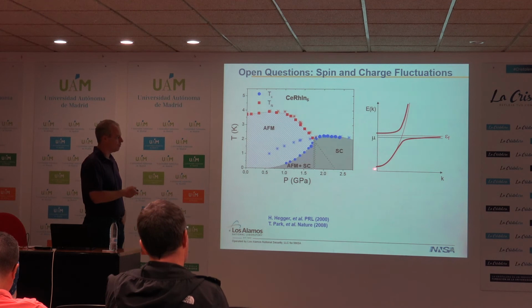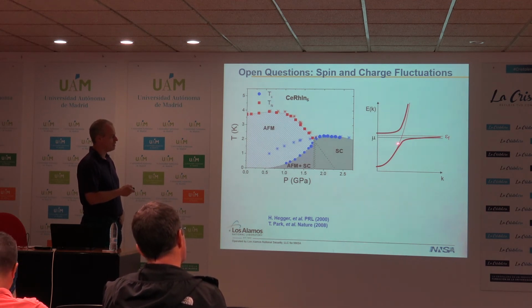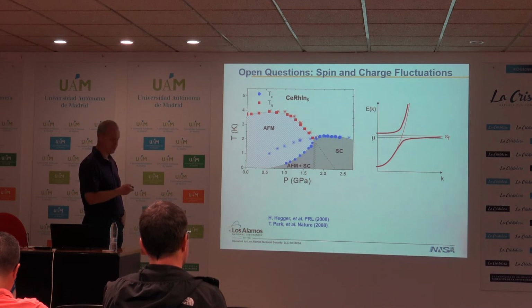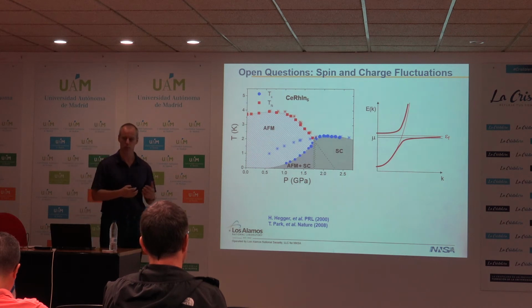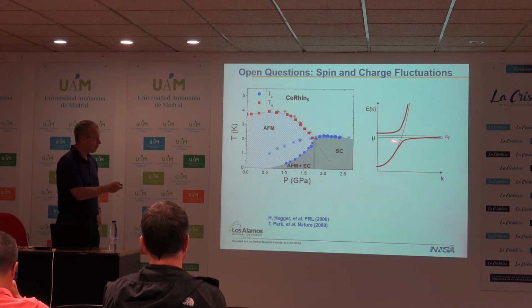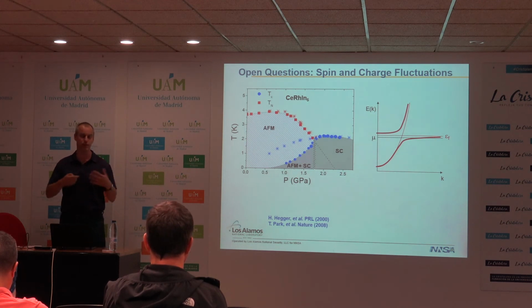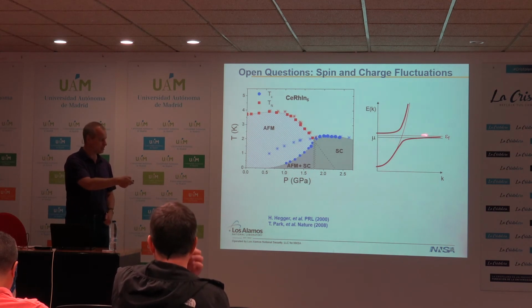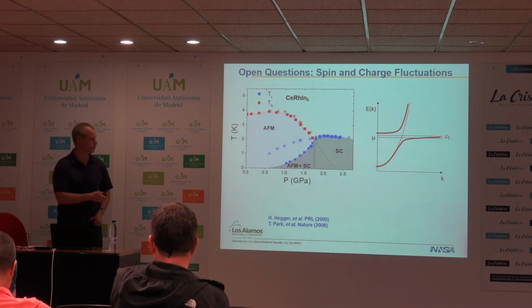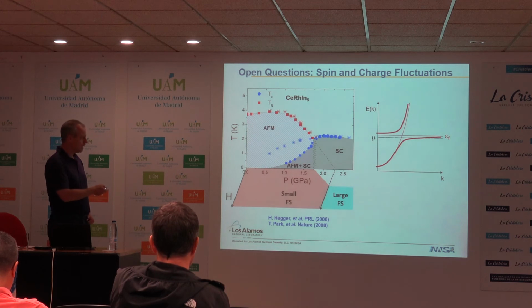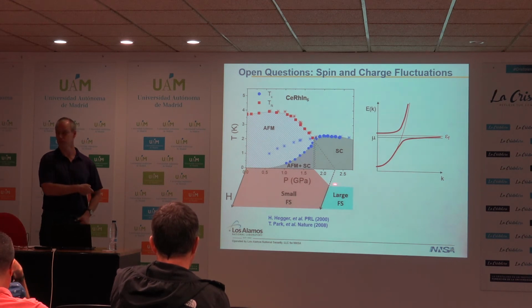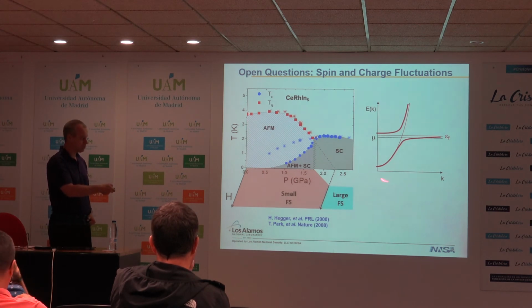If we remember this mean field picture that we have, if I had not hybridized my f-electrons at all with my conduction electrons, I would have had a Fermi wave vector sitting here. What we in the heavy fermion community call a small Fermi surface. But once we hybridize this system, we generate a new Fermi wave vector. The size of the Fermi surface increased, and it increased by one electron. So the spin fluctuations of the local moment get absorbed such that the size of the Fermi sea increases by one electron. And so you would imagine that with very small exchange interactions, you'd expect a small Fermi surface, and at some point when the exchange interaction was large enough, you'd expect a large Fermi surface.